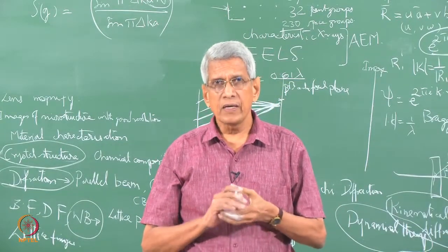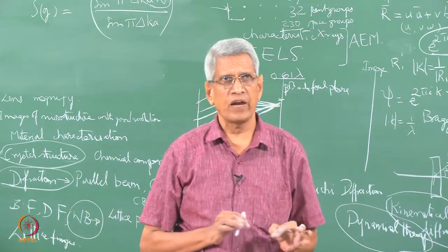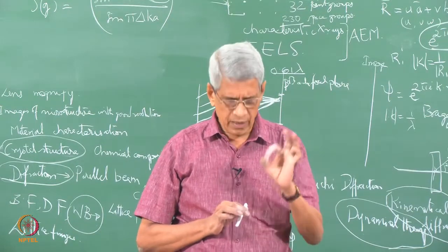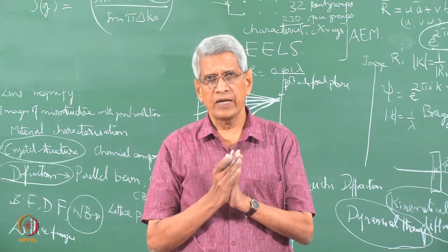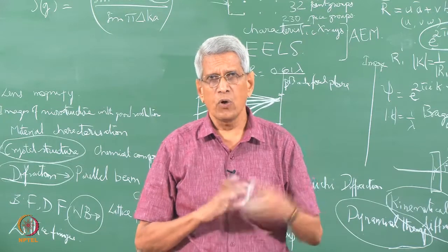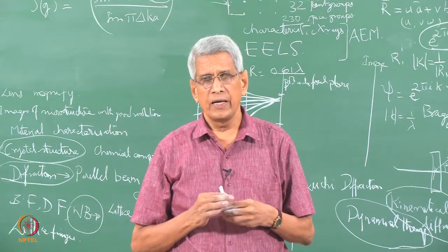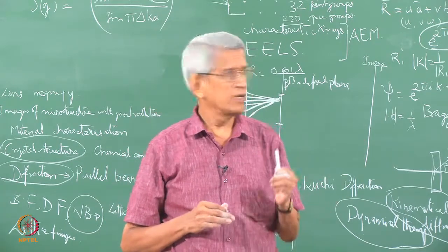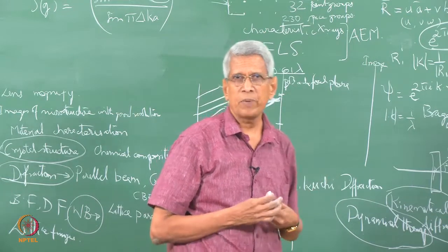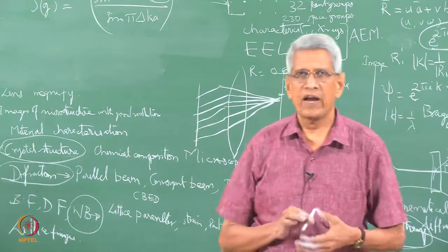Essentially what it means is that if the sample has an infinite length, then we will get a very sharp diffraction pattern, while if the sample size is very small, the diffraction spot will have a lot of broadening. In other words, depending upon the extent of sample size in different directions, we are able to get information about the shape of that sample. So, the streaking will be present in different directions in the diffraction pattern.